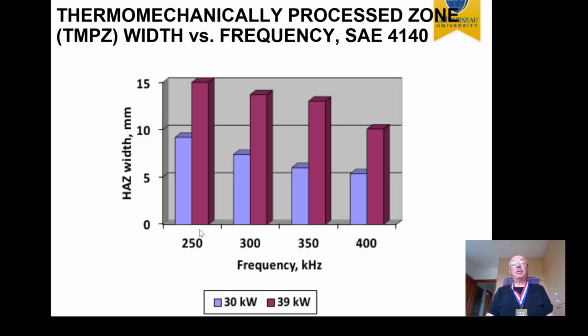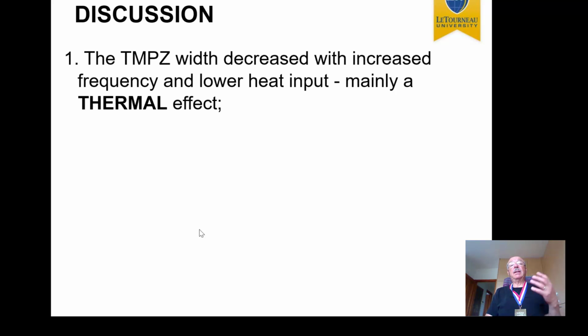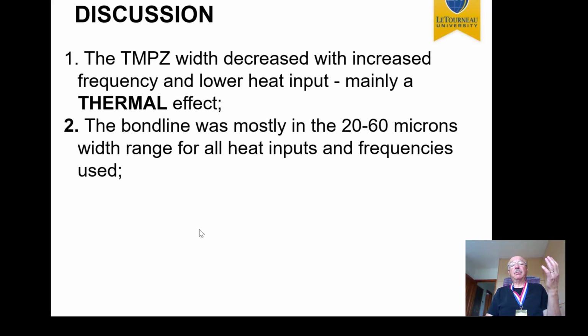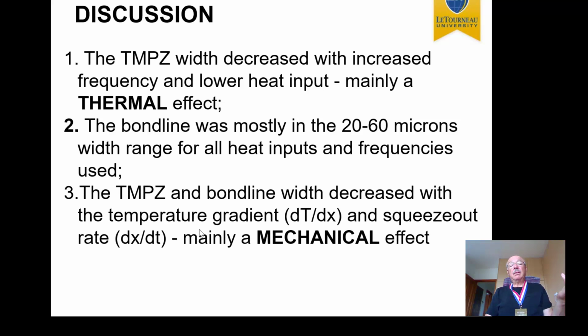Here's an example of how the thermomechanical process zone width varied with frequency. As the frequency increased, you can see the thermomechanical process zone width also decreased, but the bond line did not change much. So we started looking at the fact that the TMPZ width did decrease with frequency, so it was a thermal effect, we concluded, but the bond line was not much affected, and therefore we started concentrating more on squeeze out, that is a mechanical effect.